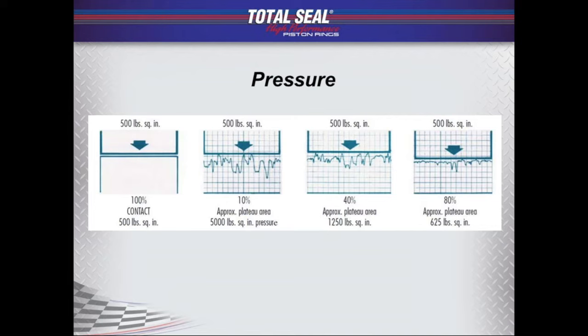If you're on the dyno and you've got one of those engines, I get guys all the time on the phone saying, hey, we're 10 pulls in, we're 13 pulls in, man, she's really starting to come in. The power numbers are starting to come up, the blow-by is starting to drop. That tells me right off the bat that we didn't have a good plateau on the cylinder finish, because the ring is doing the plateauing, it's doing the wearing, it's bringing that surface down, and every pull we put on it, it's doing that job more and more, flattening the curve and creating that plateau.